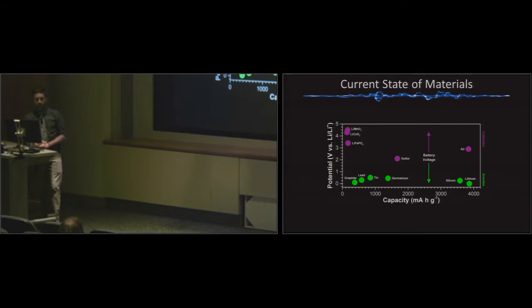So this is the current state of materials that are used in lithium-ion batteries. So the graphite and the lithium cobalt oxide I just mentioned are down here and over here. And so you see those are pretty low capacity materials compared to some of these other materials that are up there. As we move forward, we want to start pushing these materials to the right in terms of capacity so that we get higher capacity. Capacity is just the number of lithiums that you can store per weight of material. And then you have a potential, so the cathode materials have a high potential versus lithium, and anode materials have a low potential. And if you subtract those two numbers, that's your overall battery voltage.